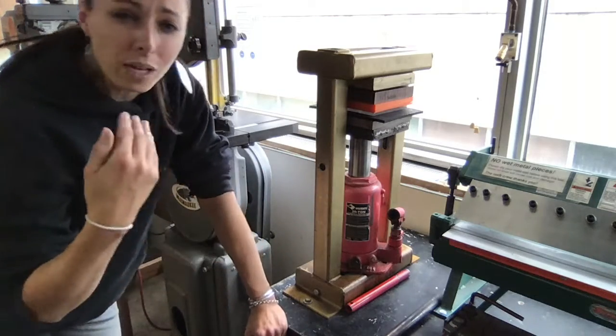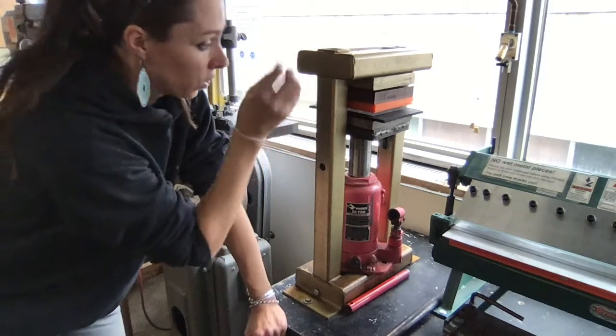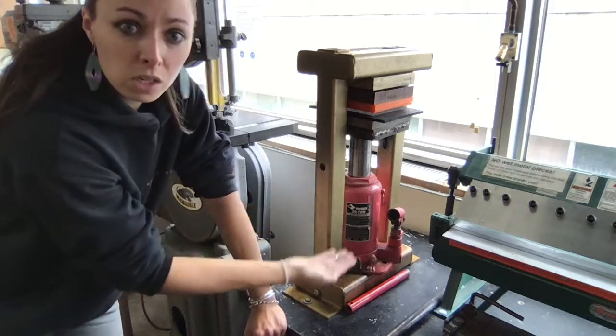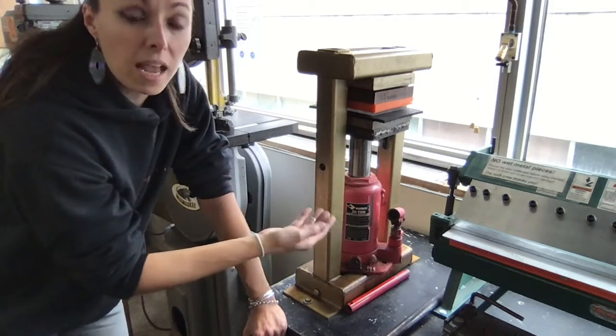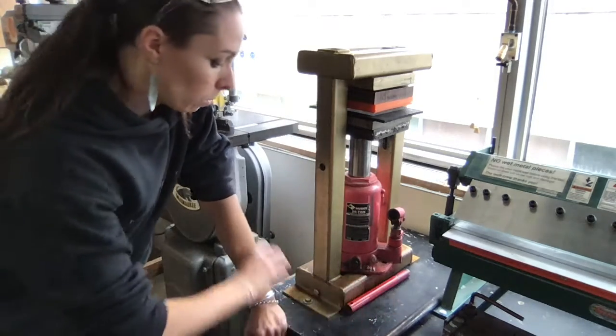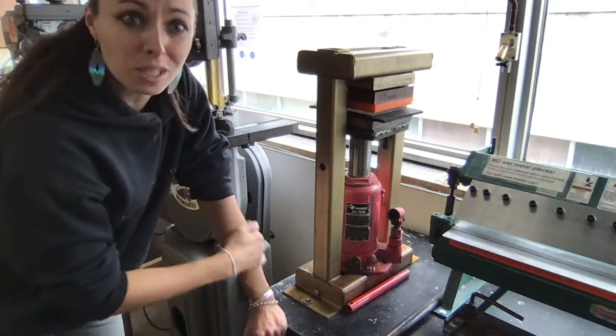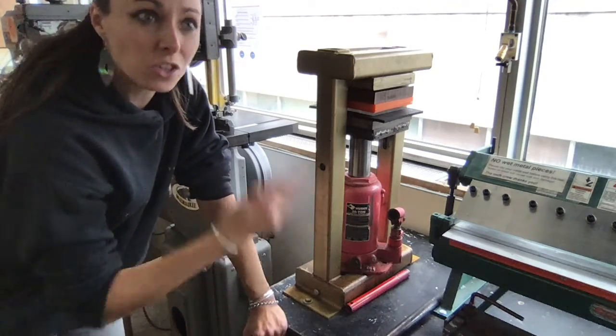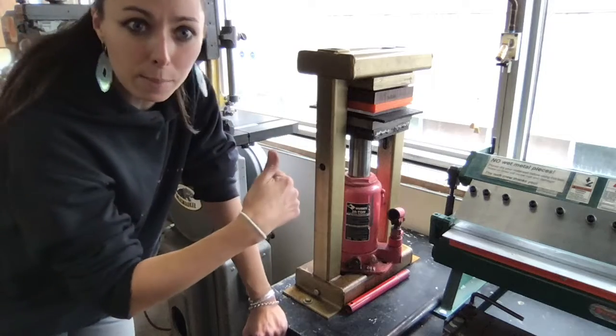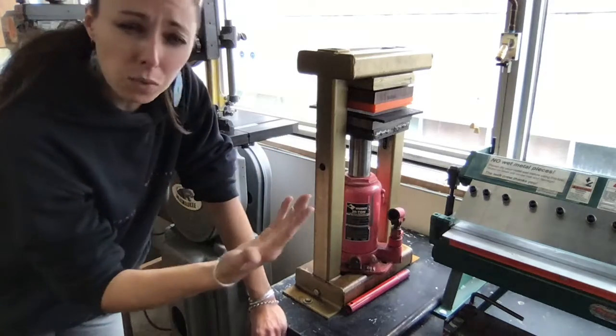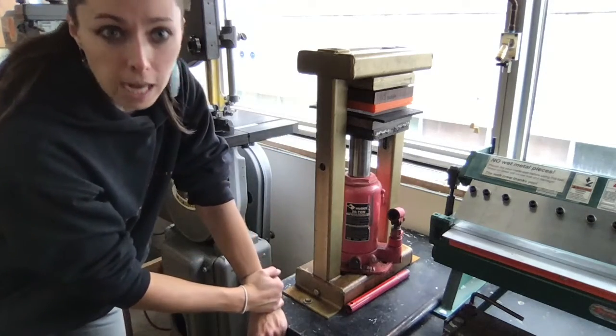So if you want to keep going deeper and thicker, then you're going to lock the press into position just like this, and then go ahead and anneal your metal. You'll want to label this so that people don't relieve the pressure on the press, because you're going to be annealing and coming back and annealing and coming back. So if you want something really deep, you're probably going to have to anneal a couple times.